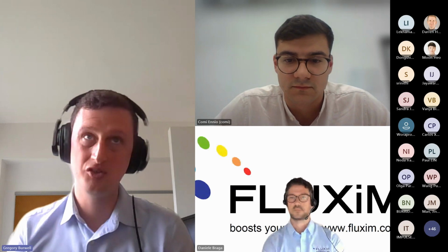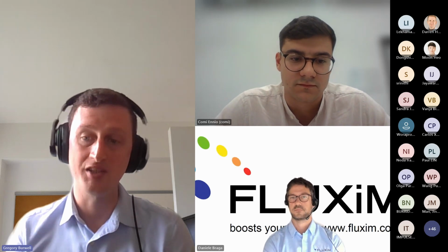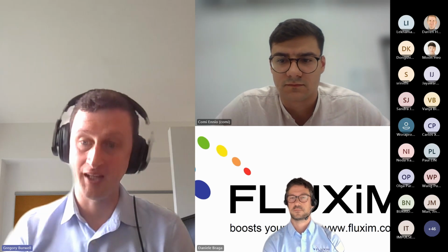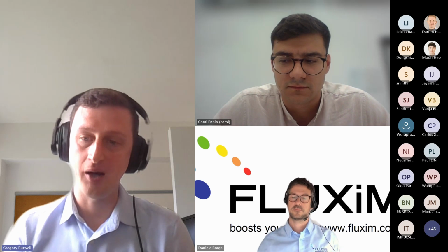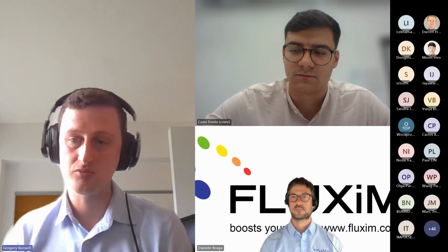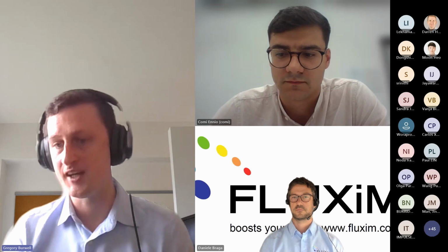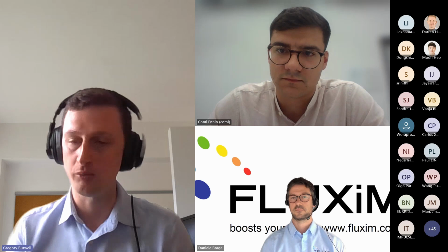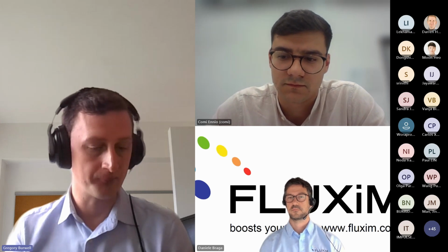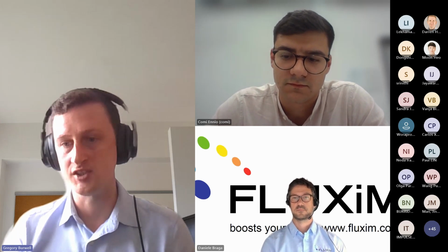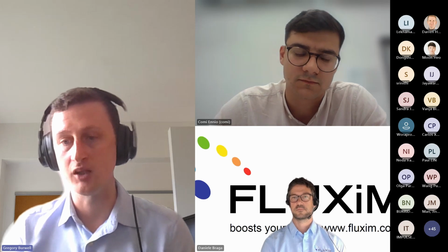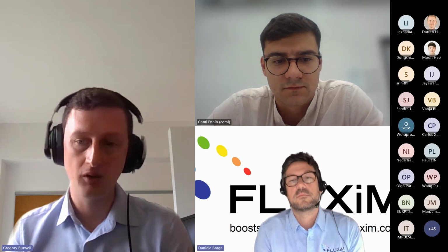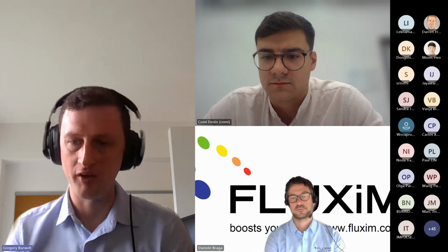So there's two different ways of thinking about that question. One is what can we simulate in terms of how does that defect behave electrically, versus how do we physically understand that source of defect? Is that something from fabrication? Is that some sort of extrinsic impurity in the solution before we've put that down with spin coating or blade coating? Or is that some intrinsic thing that's happening in the film? I think that's something that we need to understand a lot more of. I assume both of those things are happening when we scale those things. So I hope that answers your question.